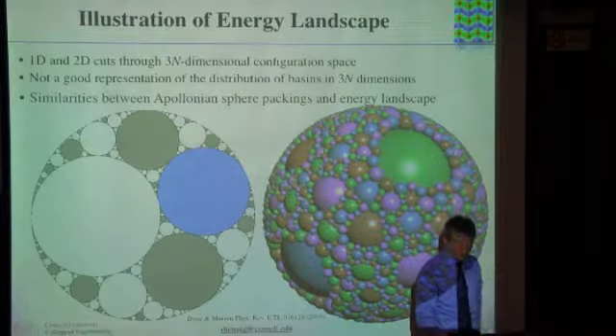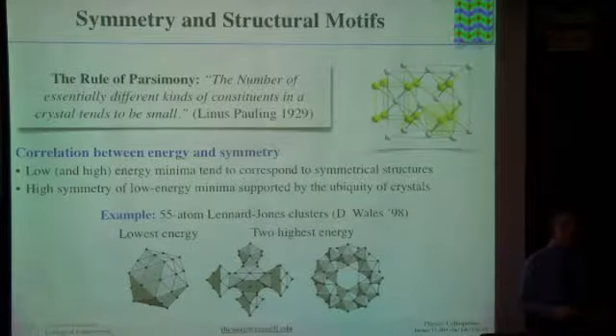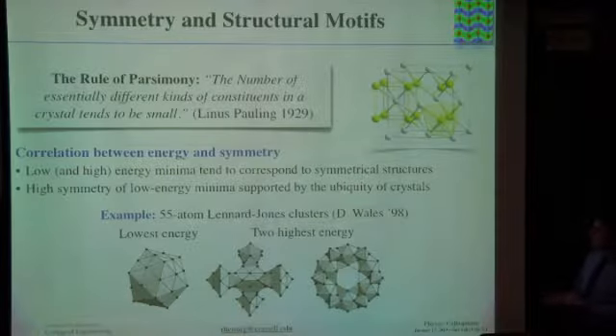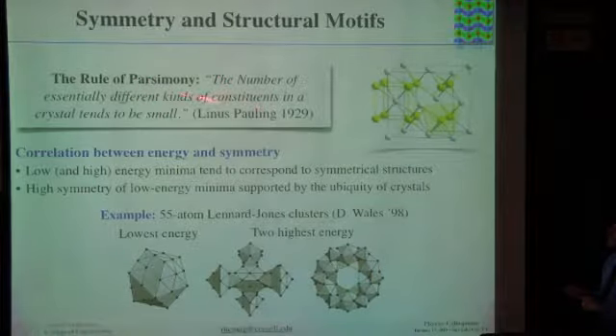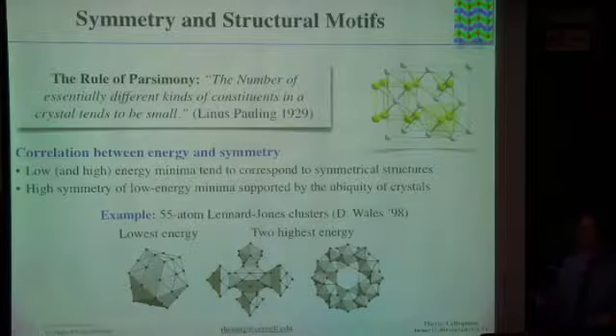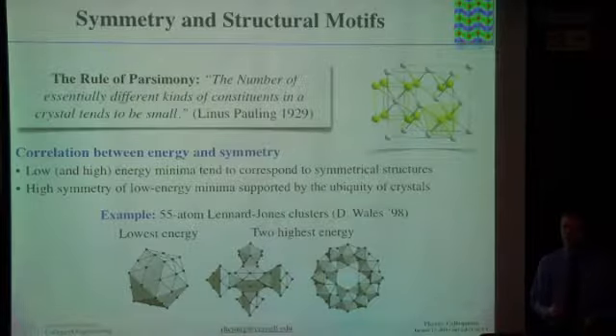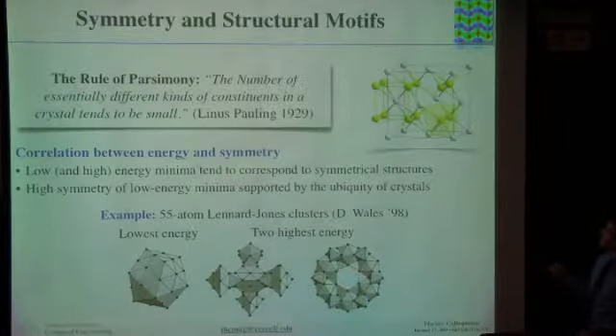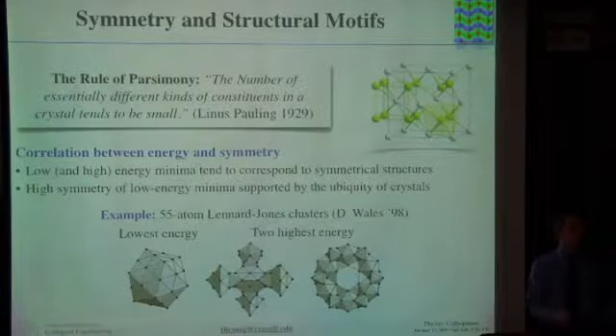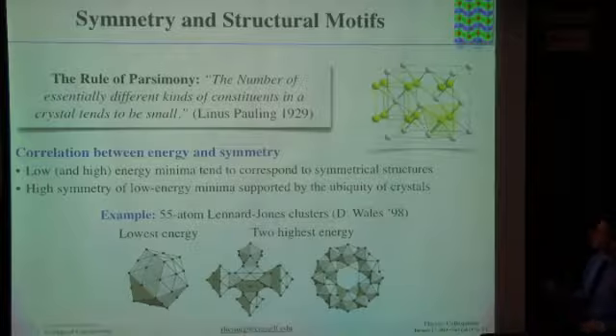I want to talk a little bit more about crystal structures, and about the fact that we know more about crystal structure than just the abstract energy landscape picture. Pauling already in 1929 noted what he calls the rule of parsimony: the number of different kinds of constituents, so different kinds of building blocks of a crystal, tends to be typically quite small. Most of the crystals we're familiar with are built out of little tetrahedra, octahedra, etc. And here's a structure of calcium fluoride. There's a cubic motif, there's a tetrahedral motif, and that builds up the structure. For most crystal structures, that actually turns out to be true, that you have a very limited number of small units which you can use to build up your large unit cell crystal structure.